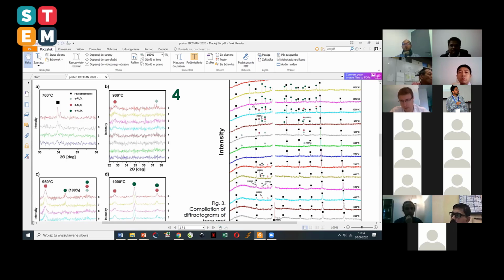And in our opinion, it is because of the formation of hematite before, and it has the same crystallographic structure as alpha alumina, and it may act, let's say, to decrease this enthalpy barrier, this enthalpy of formation, for the creation of alpha alumina.